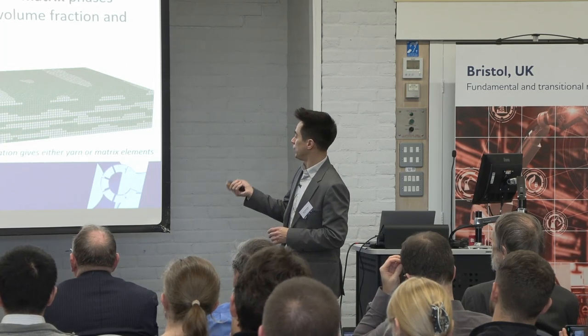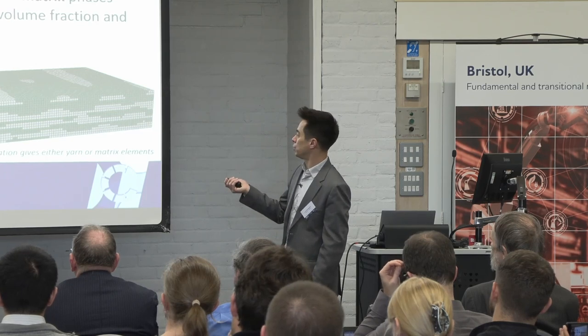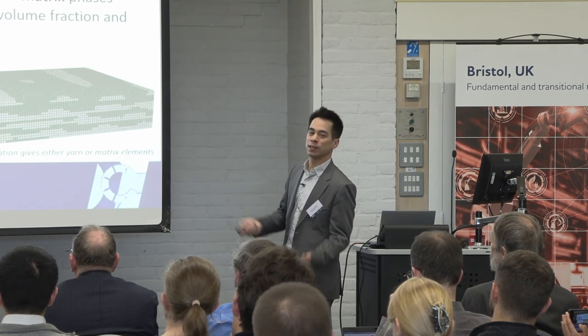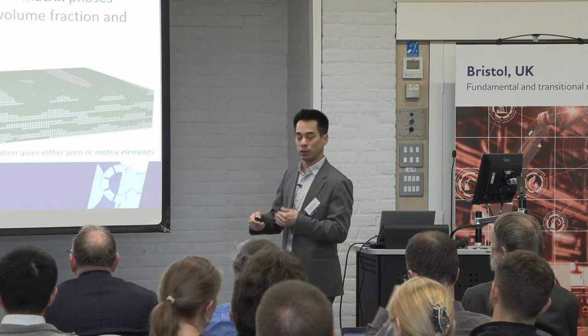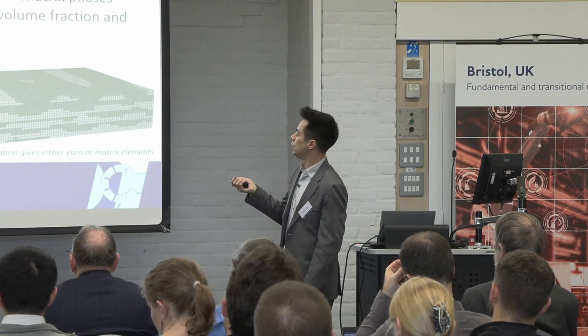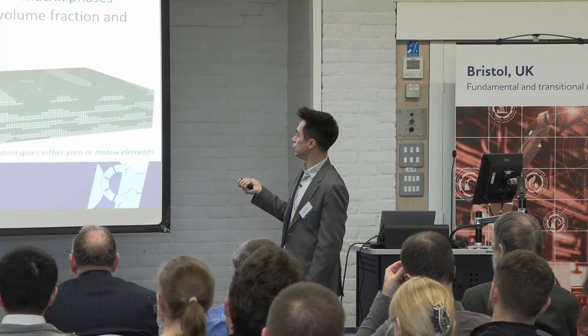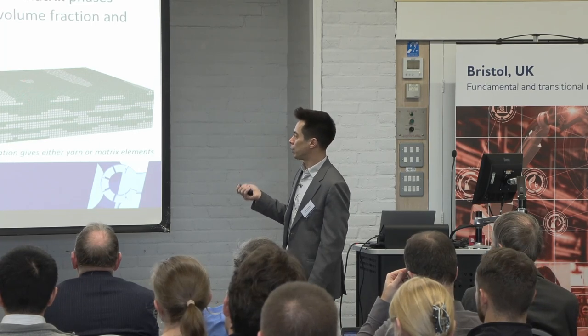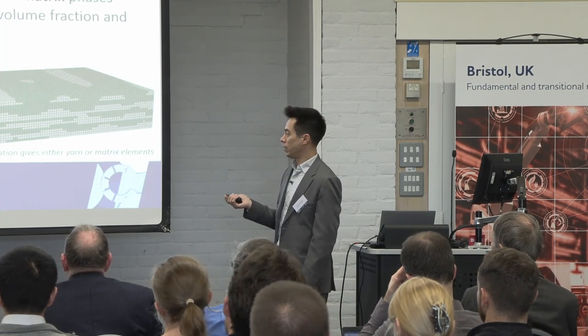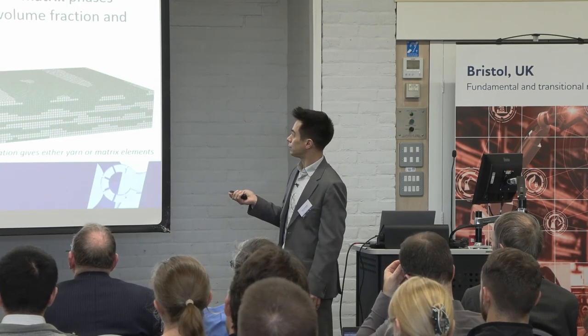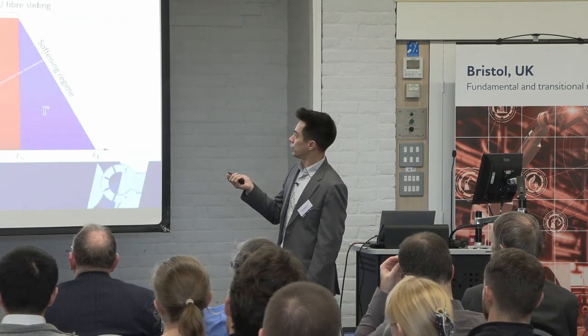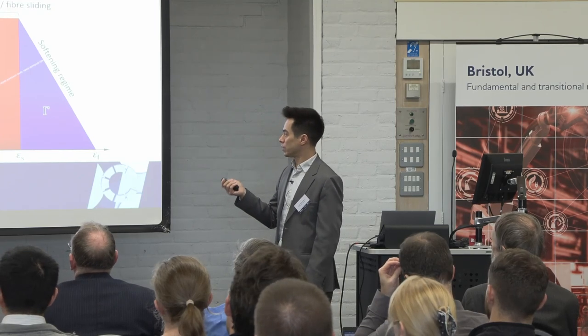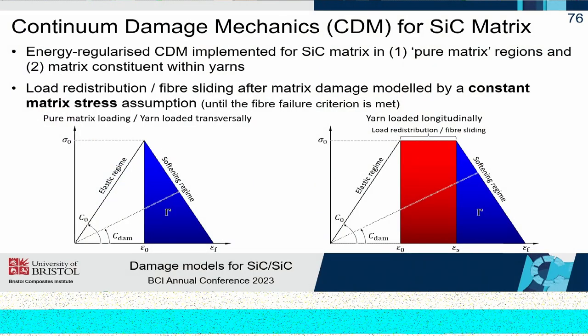And the yarn can be applied, for example, in a voxel model to certain domains that we define from the draping or weaving simulations. So you can have a voxel model made of, let's say, pure bulk matrix plus yarns at different fiber volume fractions. And then combined with the Mori-Tanaka homogenization, that's one of the novel aspects of the work, is the damage model. So it's an energy regularized continuum damage mechanics model applied mostly to the matrix material.